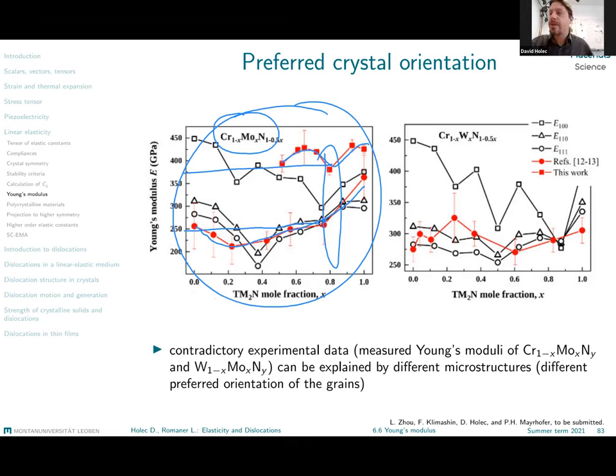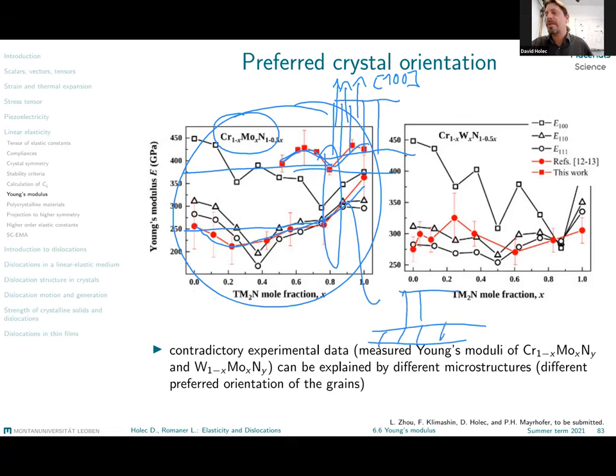And one of those, and specifically the upper one, corresponds to the grains when they grow from the substrate. This is now free surface, where they grow with a preferred direction in the 100 direction. Those lower ones, the microstructure looks very similar. Again, we have the substrate, we have the columns, but now this direction is preferably 111 direction. And here we go. If I now come with an indenter and I load my material, I load it preferentially in 111 or 100 direction.